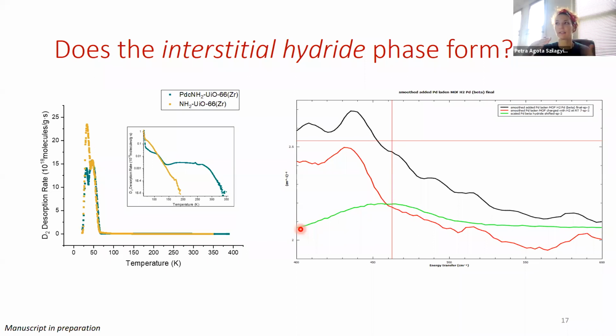And so we subtracted the former from the latter, from which we could generate an adsorbed hydrogen model. So by adding these three components up, we could generate a model spectrum which should look like this if all the palladium that was in the sample would form interstitial hydride. And as you can see, this is the peak maximum.